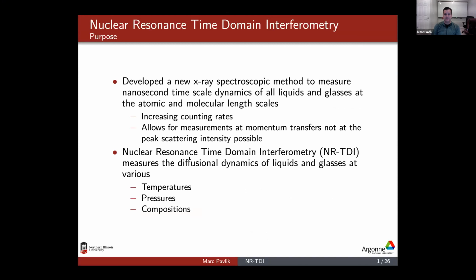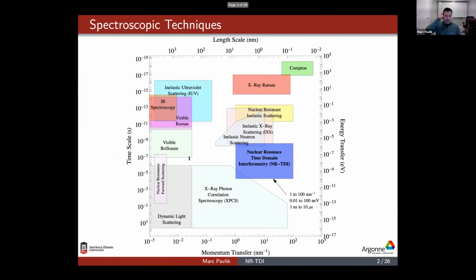So I developed a new X-ray spectroscopy method that measures the nanosecond timescale dynamics of liquids and glasses at the atomic and molecular length scales. In my research, we basically increased the counting rates, which allowed us to measure momentum transfers that were not reasonable to measure in the past. So with this nuclear resonance time domain interferometry, we can measure the diffusional motion of the liquids and the glasses at different temperatures, pressures, and compositions.